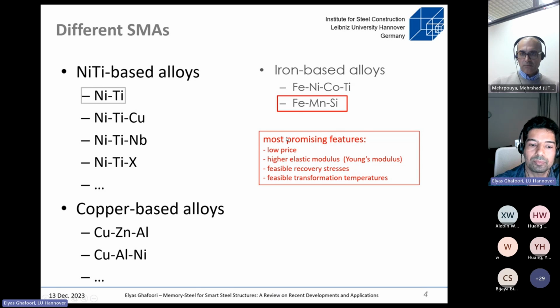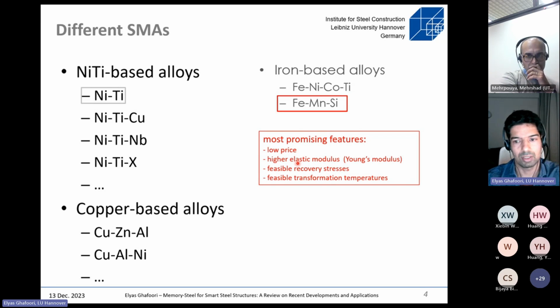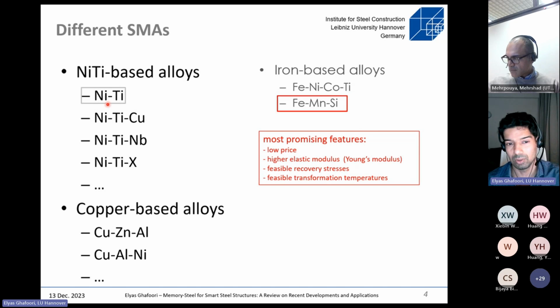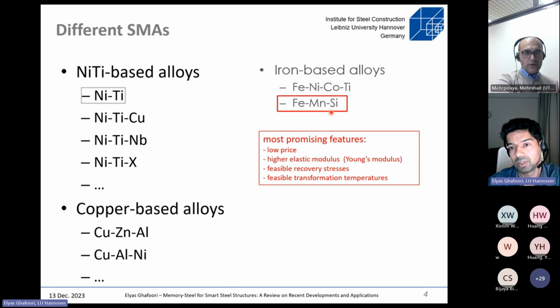Why is that important? Because the alloy has a high Young modulus. When we talk about nitinol, the Young modulus is relatively good, but it's about 30 to 70 gigapascal. With iron-based shape memory alloy, we can go up to 200 gigapascal. So it's actually good. It's in the order of steel. So you can really use it as a structural member. Also, it's very cheap. Some sorts of nitinol are expensive, sometimes as expensive as gold. With iron-based shape memory alloy, patented and developed here, we go relatively the same price scale as stainless steel. So it's still more expensive than structural steel, but it's not as expensive as gold.